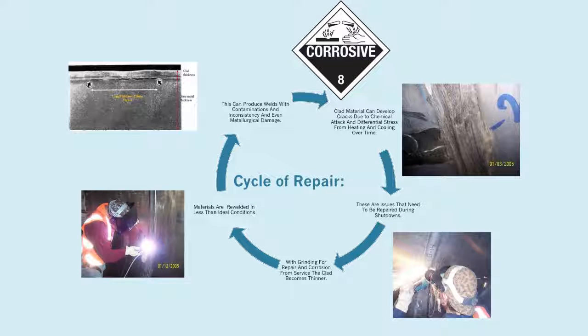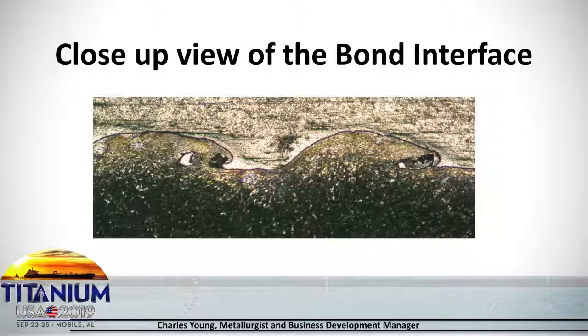Close up of the bond interface, I think we've all seen this, where the explosive bonding interface looks like a wave, and you get the titanium on the top and the steel on the bottom there. The clad testing parameters that our welding engineer, his name is Alex Orr, and he's from The Ohio State University. Have to put the "the" in there. He had a clad that started out at 0.98 inches in thickness, and he ground it down to various thicknesses before he did some welding. And it was a 2-pass weld, and those are the parameters for the welds.